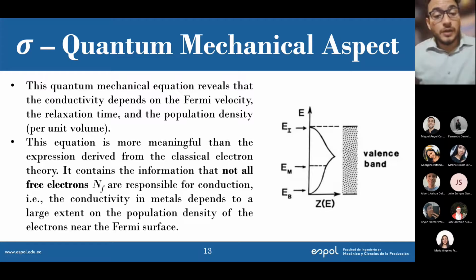The higher the velocity, the higher the conductivity. The higher the relaxation time, the higher the conductivity. The higher the population density, the higher the conductivity. So it makes sense. It's actually a lot more meaningful than the classical electron theory, because it tells us that it's no longer N_F, so it's no longer all free electrons that are responsible for conduction.